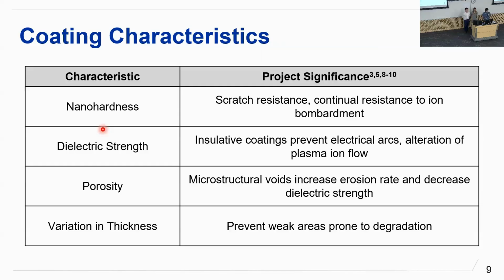So with that, the characteristics that we want to look at is nanohardness to see scratch resistance and resistance to ion bombardment, the dielectric strength, since in these dry etch chambers, they have the plasma ion flow. So we want to make sure it's electrically insulative to prevent electrical arcs occurring. As well as porosity, as I mentioned earlier, we want to have low porosity, have that green column, because porosity increases the erosion rate as well as decreases the dielectric strength, as well as have a low variation in thickness due to us wanting to have an even layer, being able to protect the material all the way across and